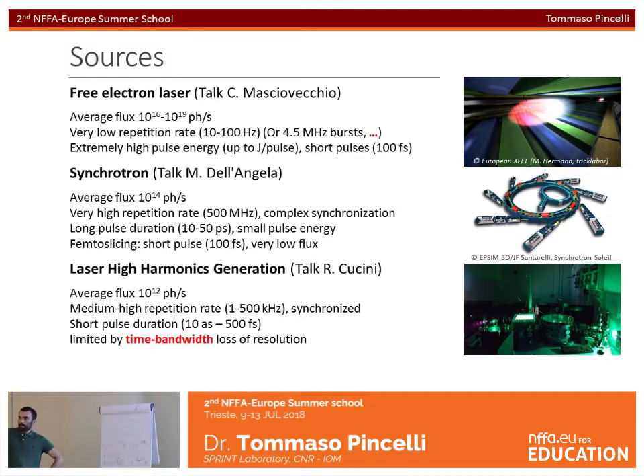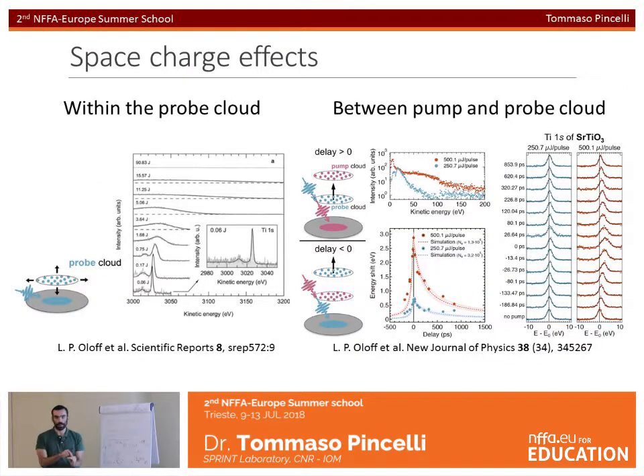What happens when you produce the emission of photoelectrons with very sharp pulses? Well, the electrons feel the fact that they are being generated at the surface of the material in a small spot all at the same time. So you create a high density of charge, and electrons start interacting with each other. And we have the simplest case, that is the space charge effect within the probe cloud. So we excite the system with a probe, and we look at the electrons, and the electrons are repelling each other. And if you look at this spectrum with increasing excitation density of power of the probe, you see that it really is destroyed completely. So this is a problem in photoelectron spectroscopy, and we have to cope with that. This is a problem in choosing the source for photoelectron spectroscopy.